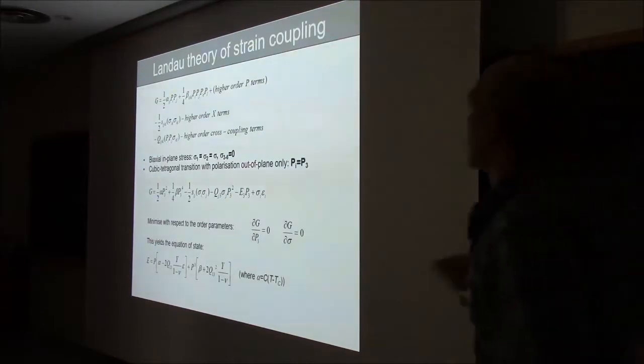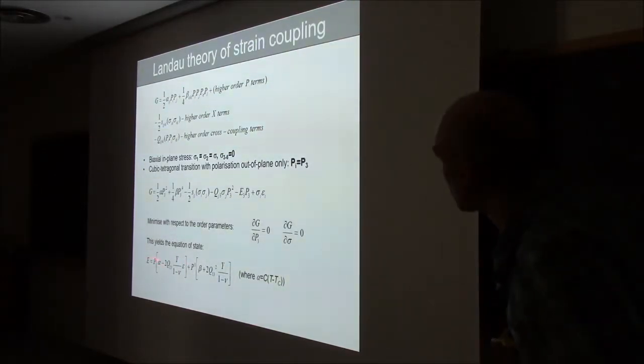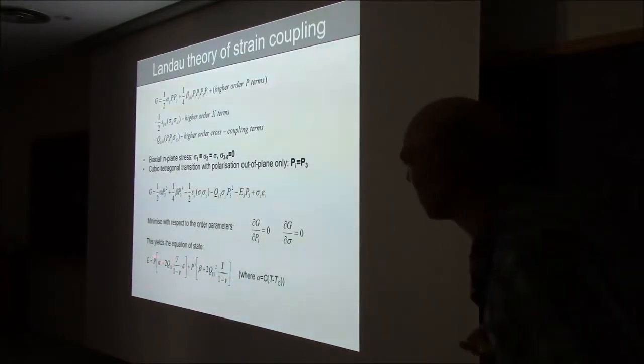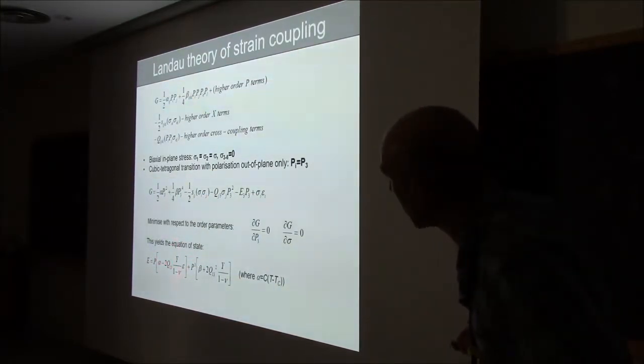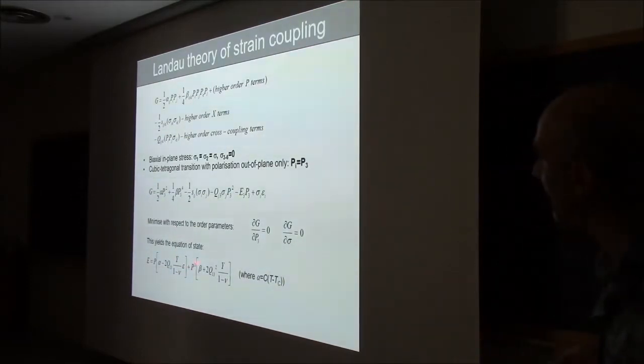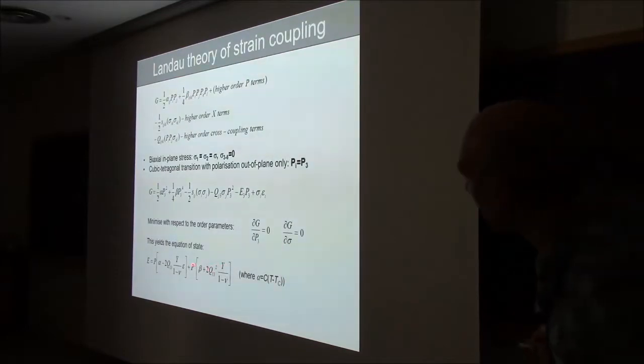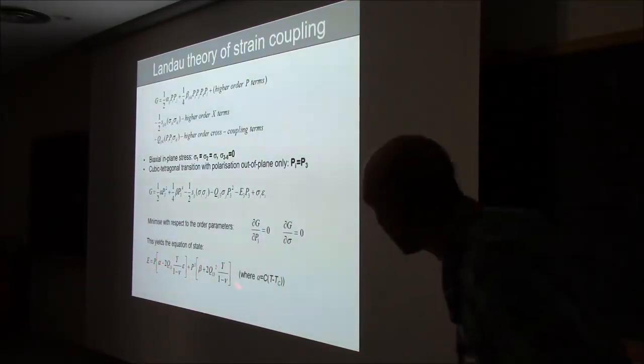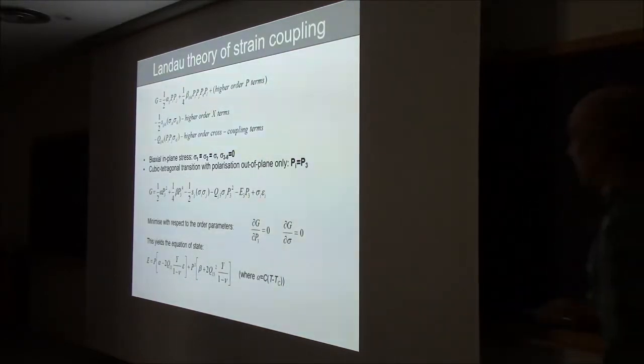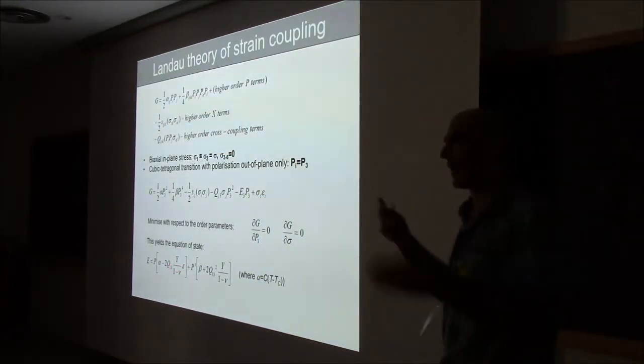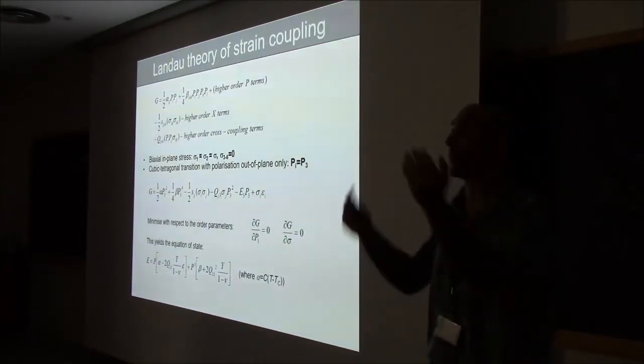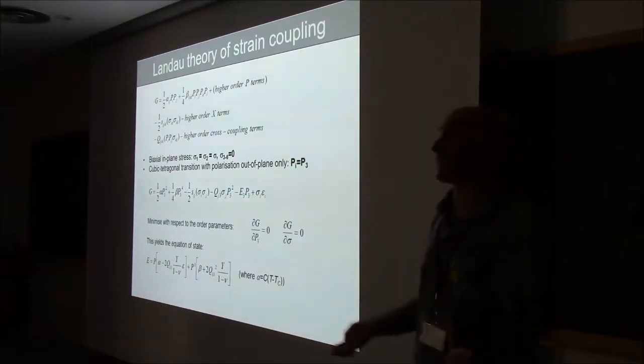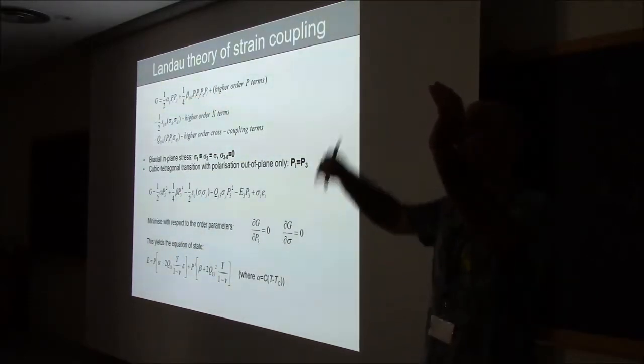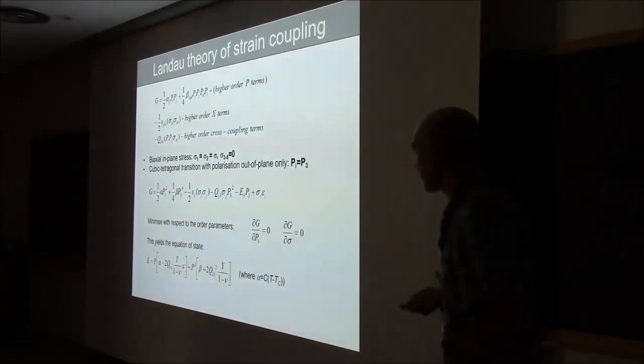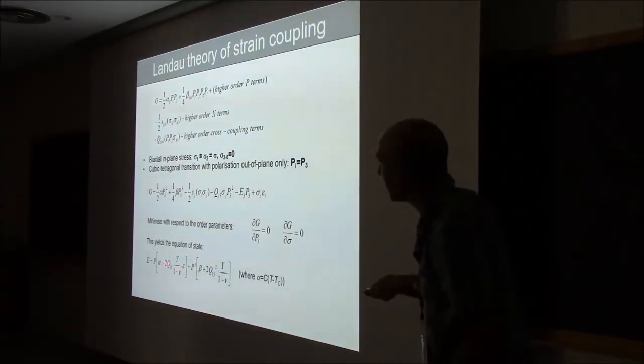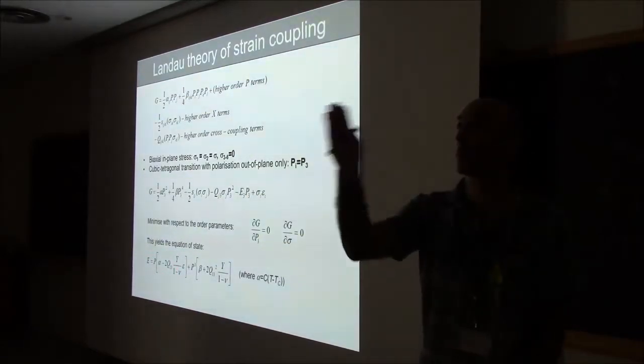Yeah? Then you do this, you resolve, and what you find is that the term multiplying p squared, that used to be alpha, now is alpha minus this thing, the electrostrictive coupling term, the Young's modulus, some constants. Okay? And the term that was multiplying p fourth now has been renormalized also. So both the alpha and the beta have been renormalized. What does that mean? Well, alpha, I forgot to mention that, alpha is the one that gives you the temperature dependence. It's the one that tells you whether you are in the paraelectric phase or in the ferroelectric phase. Alpha is the Curie constant times T minus Tc. It's the one that gives you the critical temperature. So now the strain, epsilon here, is changing alpha, so it's changing the critical temperature of your ferroelectric.